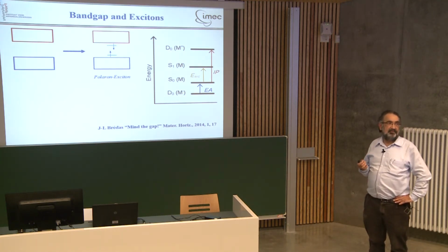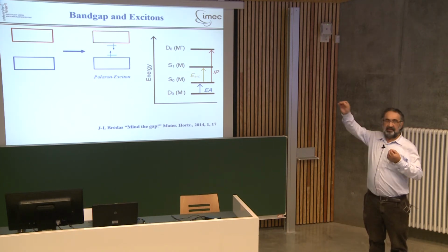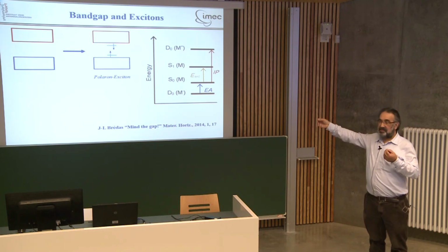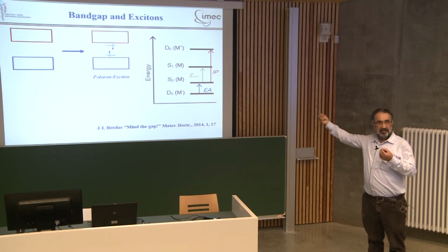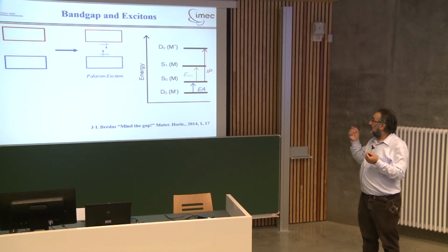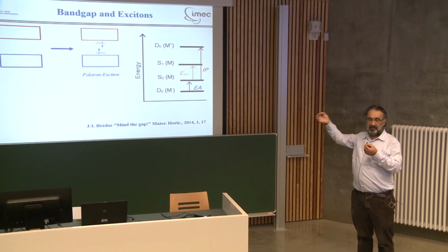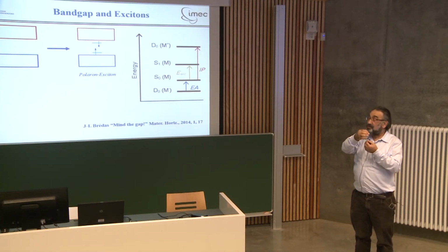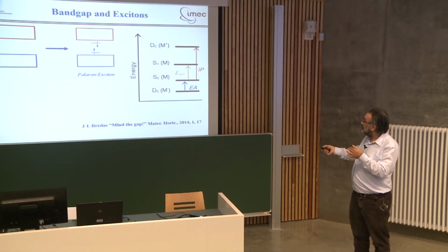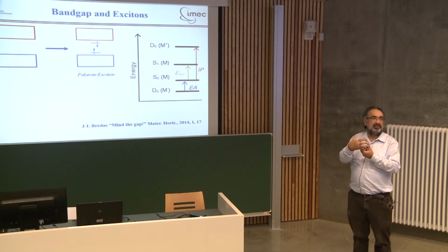And that's not true. You can imagine it very simply. What do you do with the ionization potential? You take an electron out of the HOMO and you bring it to infinity. So there's no binding anymore between this electron and the nucleus of the atom. Electron affinity is the reverse. You bring an electron from infinity close to the nucleus. So you expect a binding, and that's the reason why this is lower than that. There's a binding because it feels the nucleus.